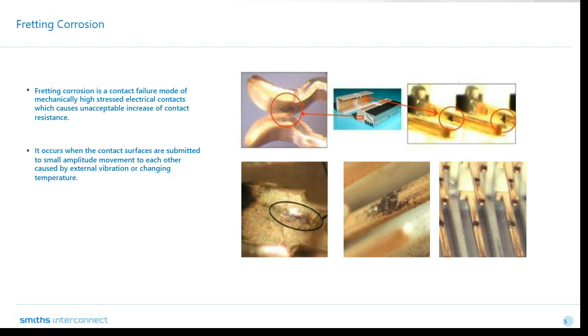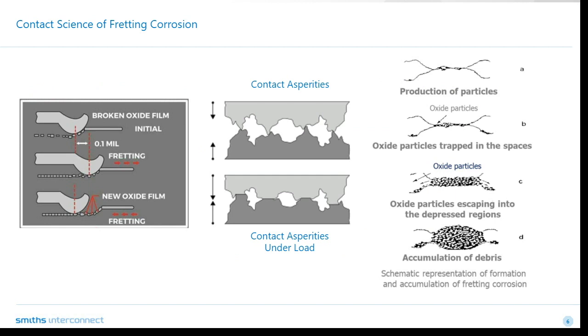So the asperities shown here in the center. As the micromotion continues, these oxides accumulate in the valleys of the asperities and insulative layers in the contact are formed, increasing resistance, which inhibits the flow of electrical current, increasing the Joule heating between the contact points. As this process continues, it leads to further power loss, signal distortion, and eventually component failure.